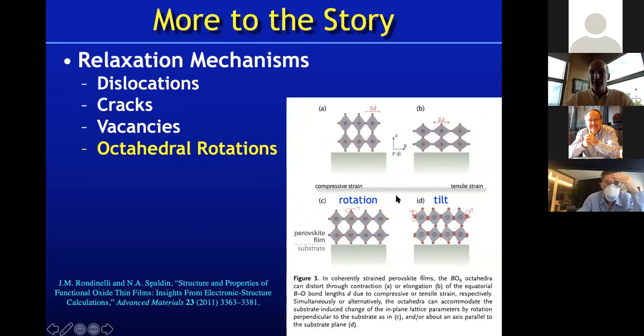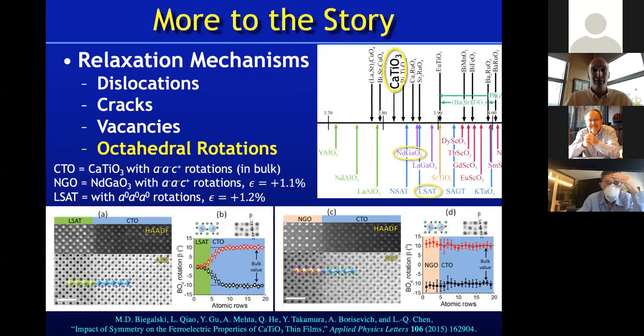If I go back here, talking about this beta angle, it's an in-plane tilt that's going to accommodate the fact that the substrate we're putting this on, LSAT, is larger in size than the film. And that gives rise to these angles that you can see are quite large, so about 10 degrees are happening.